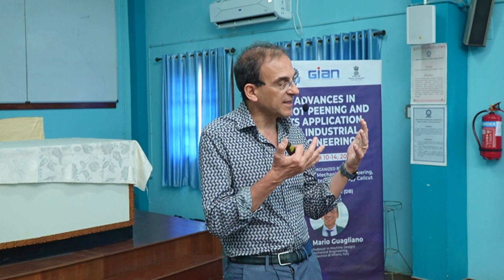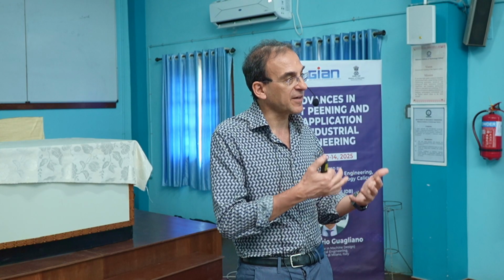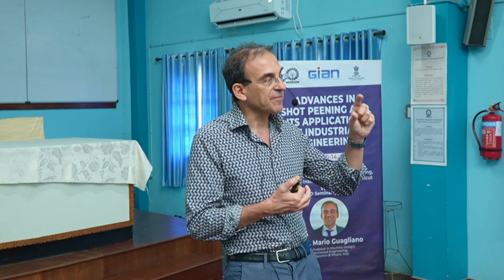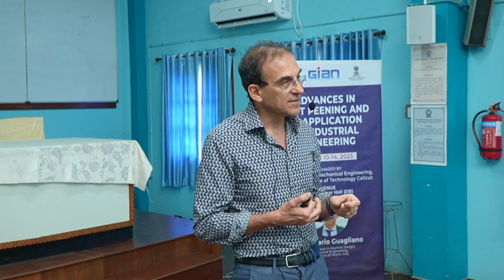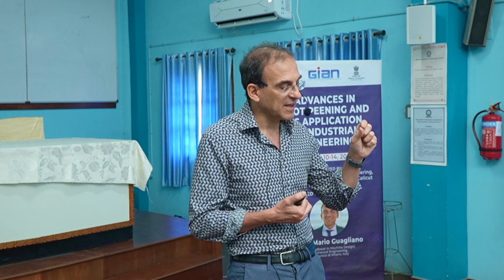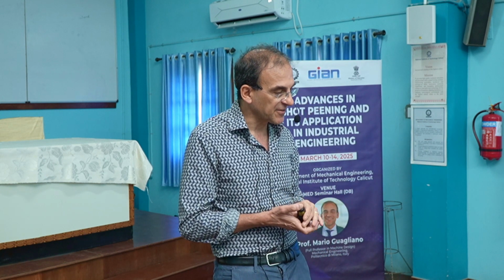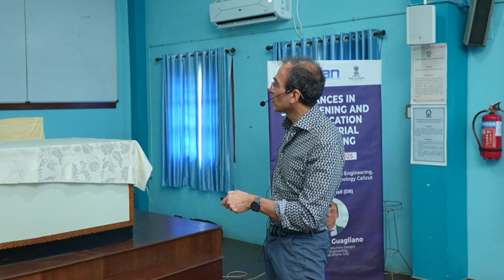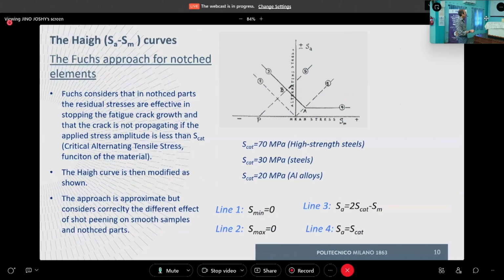And if we have a fatigue cycle where a part of the cycle itself is in compression, this will not be effective for crack propagation. So the effective amplitude is considered as the positive part of the fatigue cycle. The positive part of the fatigue cycle must exceed S-cat to have crack propagation. And so what can we notice? That if the fatigue cycle is completely positive, the limit is flat and equal to S-cat. But if we move this way, a part of the fatigue cycle will be in compression, and so the amplitude we can apply is increased proportionally to the mean stress that goes into compression. And so the limit becomes this one.